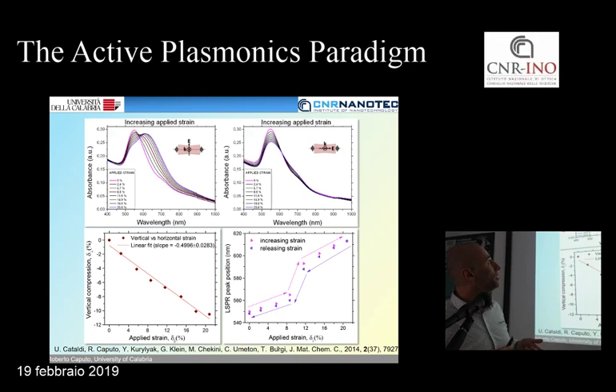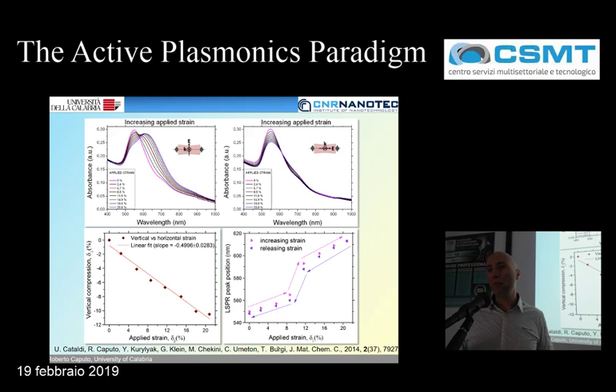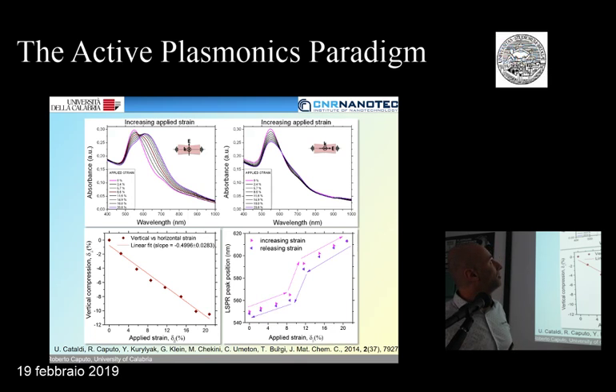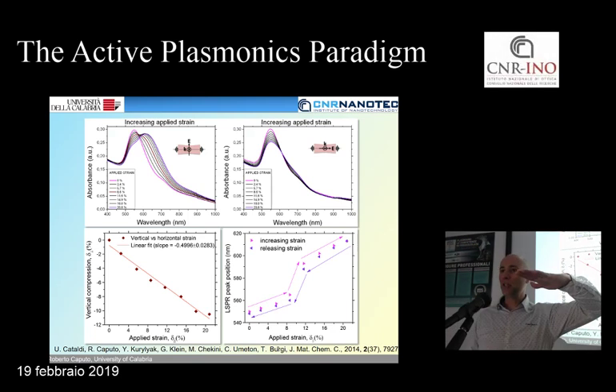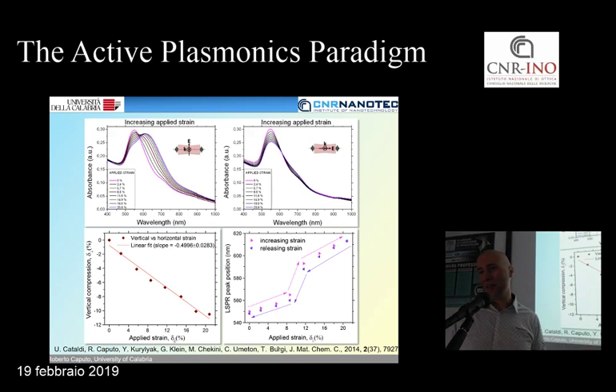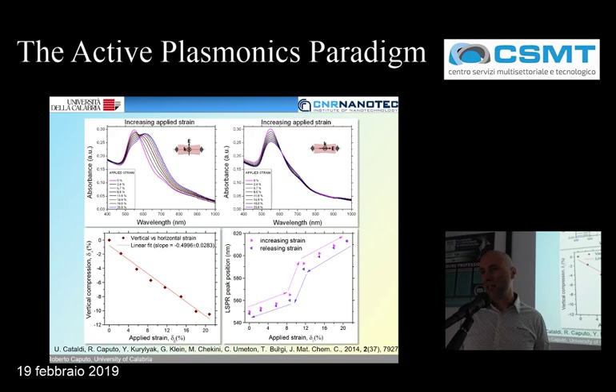And at a certain point, you have a larger peak because the number of these particles is larger than before. There is also an interesting point described by this curve, and I don't know if you can notice it, which is a different color, kind of red here at 8.6. You have a kind of plateau when these two families of particles are more or less equal in percentage in the sample. This is at least the way I explain this.